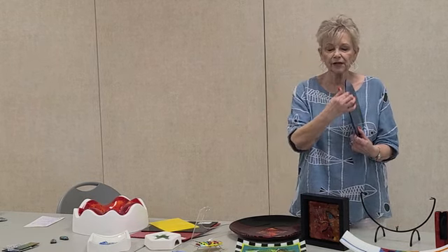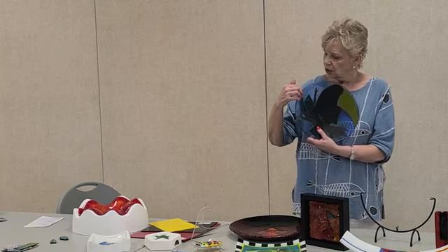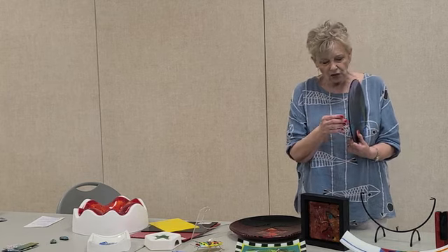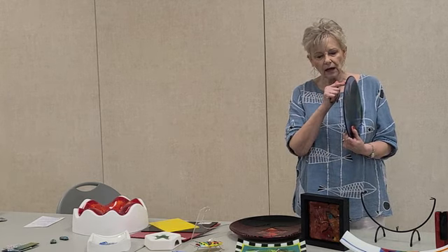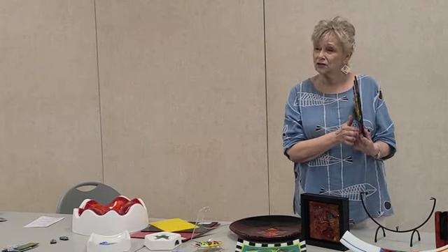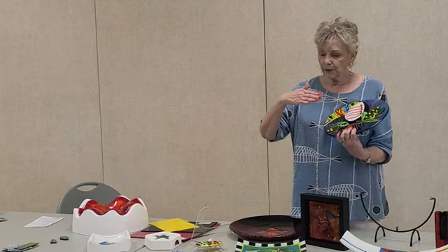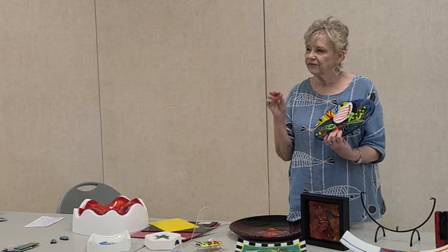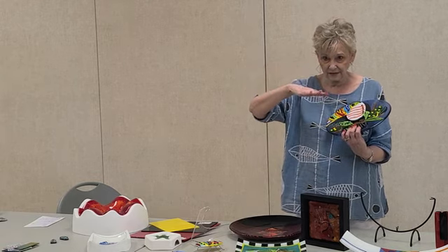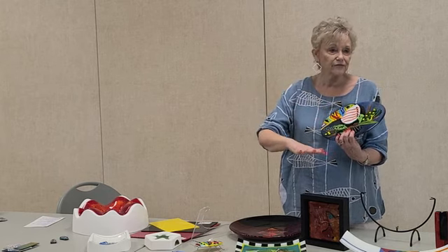And then you're going to want the two layers, a clear layer of glass and a transparent blue layer, to fuse together or melt together so that you don't have a bump, like mumps. I call them mumps. They're kind of like swollen places where the glass gets trapped in there. So in your fusing schedule, you would put a step where it went up very, very slowly, so that the whole time that top layer is falling more like this, rather than the edge falling first and trapping that air inside and then falling down.